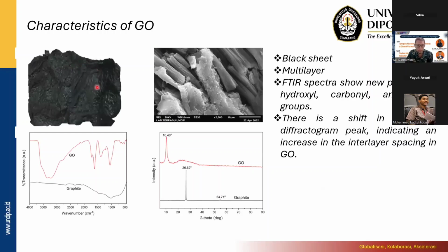This is the GO sheet, and you can see this is the FTIR of the graphite, and you can see that the graphite already changed to GO, with more functional groups here, and also the XRD shows that there is a shift from the right to the left. Yeah. Let me continue. So there is a shift from the right to the left. It means that the interlayer spacing of the GO is larger than the graphite.